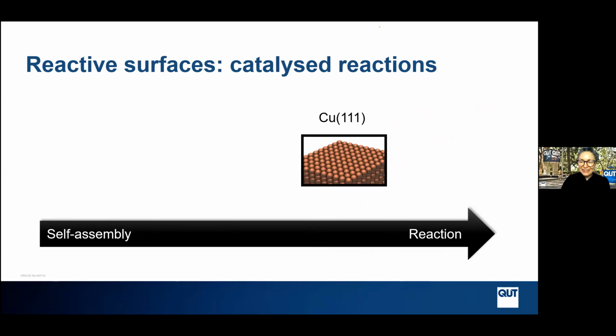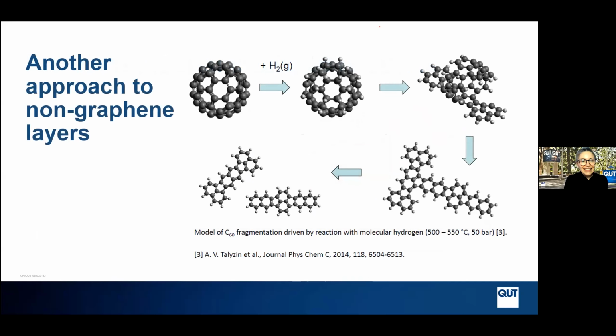Just one more note about those C60 films. Steve's actually working on those to look at them as a basis for another approach to non-graphene layers. I say non-graphene because Steve's work is in looking at intrinsically defective layers. We're really interested in how much crystallinity contributes to the electronic properties we see. Our intuition says not much, so we're interested in looking at whether we can actually control the level of defectiveness or disorder in a film and measure the effect that that has on these electronic properties.